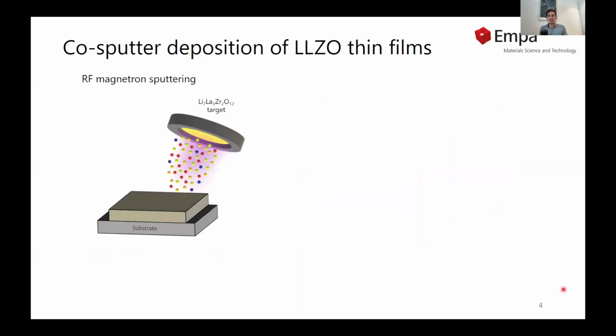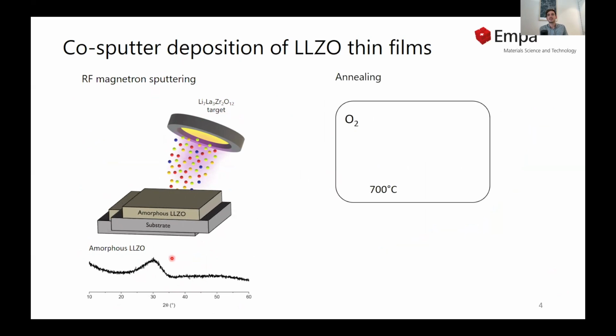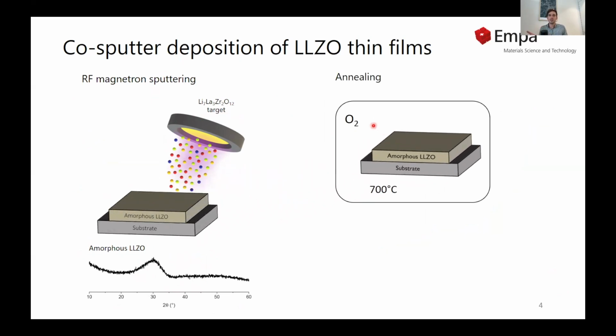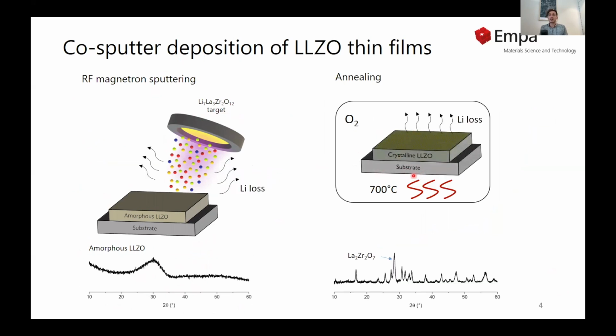In our work, we investigated an RF magnetron sputtering process to fabricate LLZO thin films with equivalent properties to the bulk pellets. We used a stoichiometric LLZO target, which we sputtered in argon and oxygen to form an amorphous LLZO film on a substrate. Here, the XRD shows the amorphous phase of the as-deposited films. In order to crystallize them, we process these films in oxygen at 700 degrees for about 1 hour. However, due to the lithium loss occurring both during the sputtering process and the annealing process, what we observe in such films is the formation of non-conductive lithium-deficient phases, specifically lanthanum zirconate.